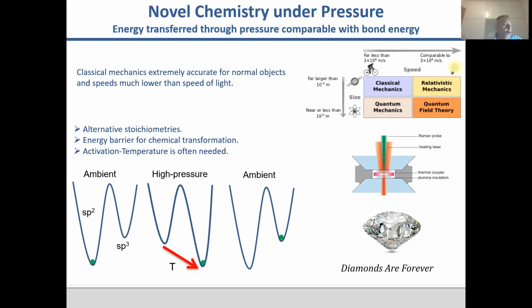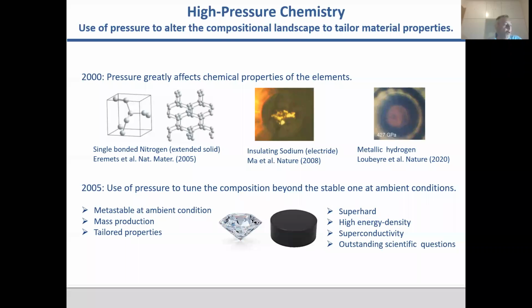So I would say at the beginning, there were a lot of examples of elements that completely change their chemical properties or bonding under pressure. Some well-known examples are the synthesis of the single-bonded form of nitrogen in 2005, where instead of the covalent molecular nitrogen you have an extended solid, or the insulating sodium at about 200 GPa, if I remember, which forms an ionic solid, in reality an electride, and also some recent examples of metallic hydrogen. So the idea here is that if simple elements can show different properties under pressure, maybe we can go a step further and apply these new chemical rules in compounds.